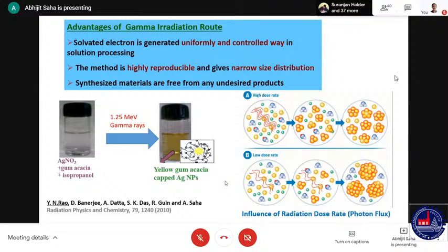So if a very large number of gamma photons are coming in a very short time, we call it a high dose rate, otherwise a low dose rate. That is basically nothing but the photon flux: how many photons per square centimeter per unit time. And that can also have an effect on the synthesis of nanostructured materials. If you have a high dose rate, you get a more uniform, smaller structure. If you have a low dose rate, you get a much bigger structure. So for uniformity in smaller structures, a high dose rate is desirable. A low dose rate can give a much bigger particle size.